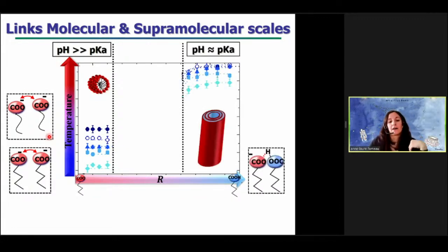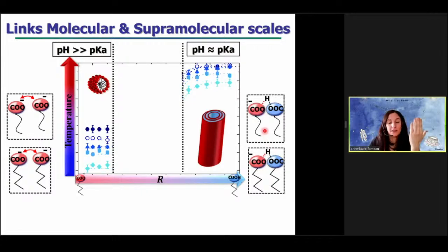Then when you increase the molar ratio, at high molar ratio, you have an excess of fatty acids in comparison to the quantity of counterion. So the pH is close to the pKa of the fatty acids. At low temperature, you have a mixture of fatty acids in ionized state and protonated state that interact by hydrogen bonding between the head groups. And you have the alkyl chains in a gel state. You increase the temperature, you have the alkyl chains that transit from the gel state to the fluid state, but you still have the head groups that are bound together due to the hydrogen bonding. So you still have tubes in solution. But then at very high temperature, the hydrogen bonds can be broken.